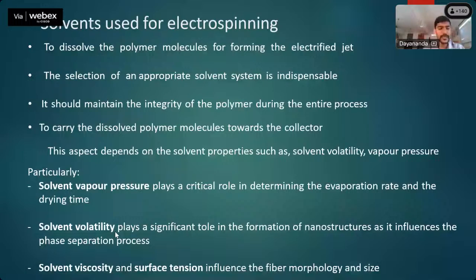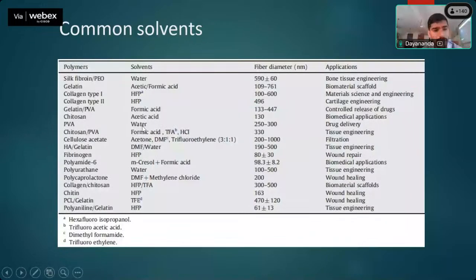Viscosity and surface tension also influence the fiber morphology and size. These are some of the choices for selecting a solvent. For example, polyvinyl alcohol - we are all familiar with this - if you want to make a nanofiber mat of it, you have to dissolve it in water. But in most cases chitosan is very difficult, because even a small chitosan solution has very high viscosity. You might have encountered this same problem - if you prepare a concentrated chitosan solution, it won't even come out from the needle because it's too thick. So these are the polymers and their corresponding solvents.